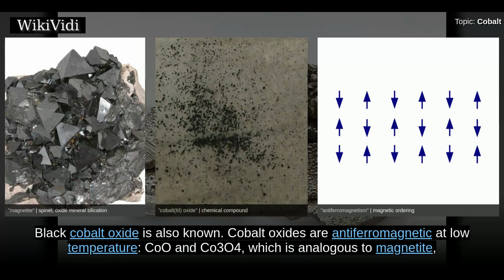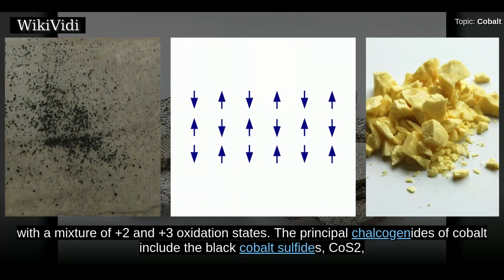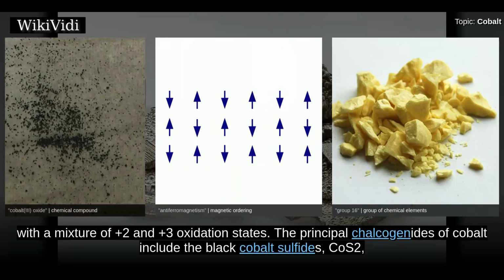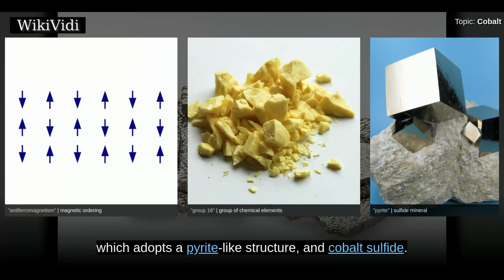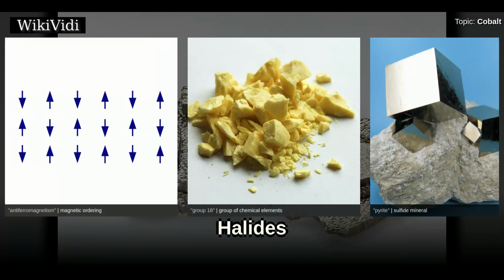Cobalt oxides are antiferromagnetic at low temperature, CoO and Co3O4, which is analogous to magnetite, with a mixture of +2 and +3 oxidation states. The principal chalcogenides of cobalt include the black cobalt sulfides, CoS2, which adopts a pyrite-like structure, and cobalt(III) sulfide. Halides.